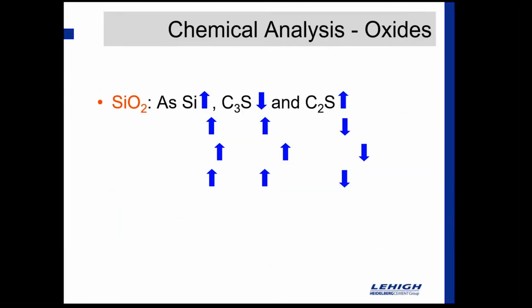And so one of the things that we're asked a lot when we do our concrete training events here at our plant at Mitchell is, well, why can't you make a cement that's high early strength and high late strength? Why can't we have our cake and eat it too? And some of that is related to the generation of these oxides and how they impact those Bogue equations. So if I raise my silica content, my C3S, my early strength, is going to go down, but my C2S is going to increase. So if I raise my silica, there's a good chance that I'm going to bump up my 28-day strength.